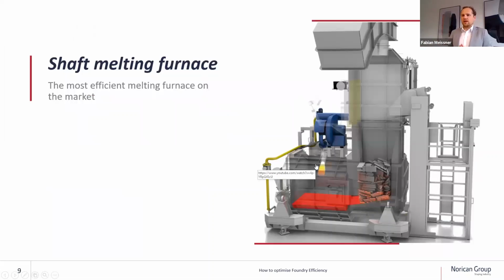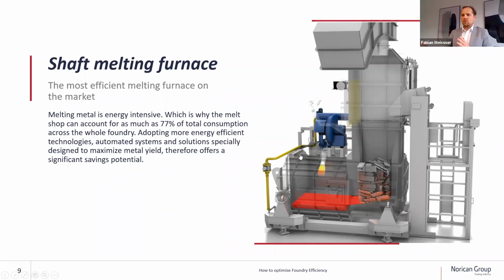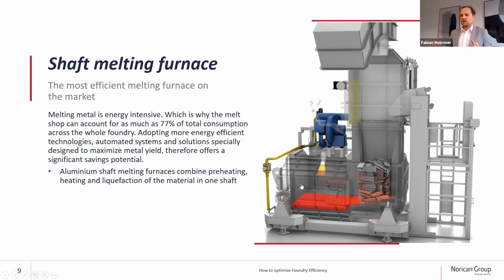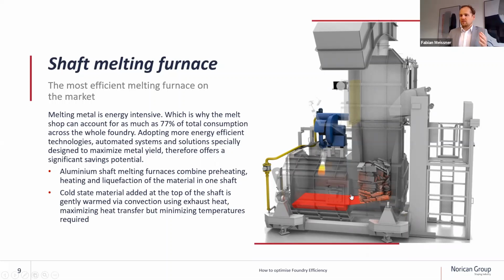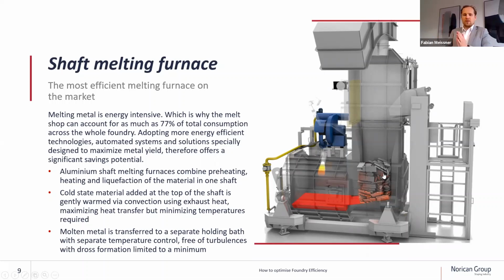As mentioned, it's a shaft melting furnace. So what is a shaft melting furnace? A shaft melting furnace is combining the preheating, the heating, and the liquefaction of the material in one shaft. So we are using the combustion heat from the holding bath to preheat the material in the shaft. This enables us to use much less energy, or to consume much less energy, and to achieve a much lower metal loss